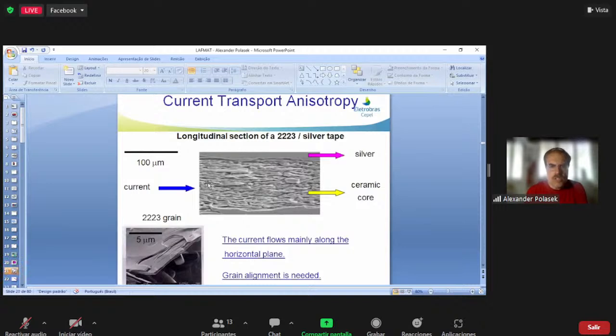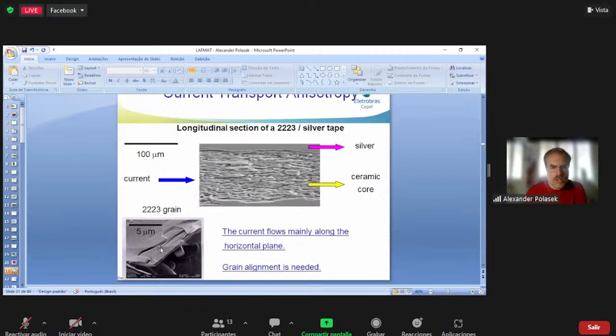And you need this section of first generation tape that we produced once at CEPEL, and you can see a longitudinal picture, and you need the grains aligned in the current flow direction. And here the example of the one grain, there are plate-like grains with a high aspect ratio or high anisotropic morphology.